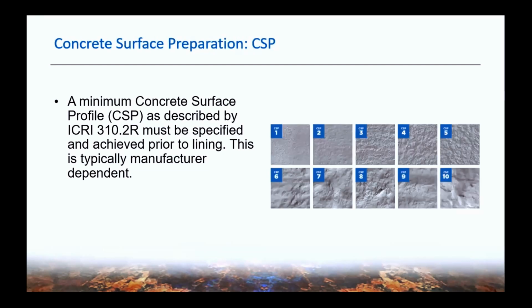So here's a good visualization of these different CSP levels. Naturally, as your films get thicker, a greater CSP is generally going to be called out, and there's different means and methods to get to the different levels of concrete surface profile. But most any product that's going to be sold for concrete substrates is going to have a CSP level called out on the data sheet of that product. If not, it's something that needs to be clarified, because this is very important, because much like with steel, there is a big difference in performance with the lining system, and a lot of that's going to be dependent on the surface prep. So making sure that you have the proper surface prep conducted first, and having that proper profile first is going to be very important.